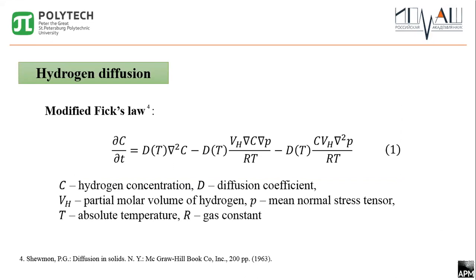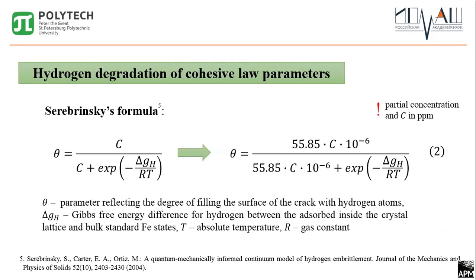Within the HEDE model, the process of hydrogen transport inside a solid is usually considered as a diffusion process. To describe it, Fick's law is applied, modified by the additional term that takes into account the thermodynamic or chemical potential. Considering the effect of mechanical stresses, it can be written with an additional term. At the next stage, the fracture criterion associated with the crack opening displacement is considered. According to Gorsky's law, when the sample is loaded with the tensile load, hydrogen is concentrated in the region of the maximum average normal stress, where the adhesion of the crack edges decreases.